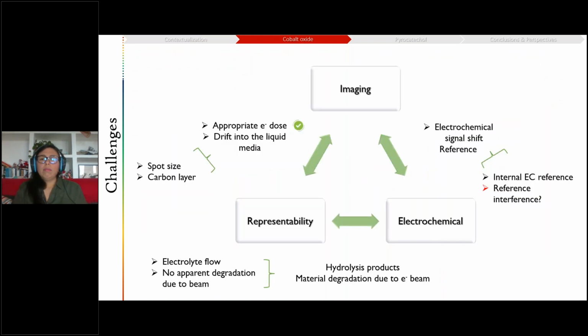So, of course, I mentioned it before, there are a number of things to take into account in order to have representable data once you do your observation. So there are three things that we need to take into account: that the imaging parameters are good enough in order to be able to observe something, right? That this data is representable, that it actually corresponds to what the processes ex situ could be, and that the electrochemical window that we are using is also representative of what we would use in a typical cell. So we try to optimize all of these parameters throughout our experiments. We show you some of the things that we took into account.